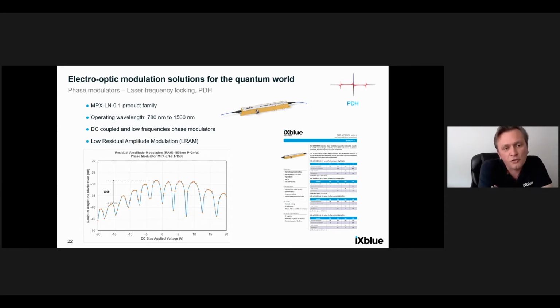Here in this slide, we show the measurement that we took on the graph on the bottom. We measure the residual amplitude modulation in dB versus the DC voltage applied, from -20 to +20 volts. You can see that there's some ringing happening, but ultimately you can find a sweet spot that is 10 dB better than what you would get if you didn't correct for that problem. So we offer solutions there over a wide range of wavelengths, from 780 nanometers to even 2 micron. We offer low residual amplitude modulators, which are DC coupled and typically come with a high impedance input.